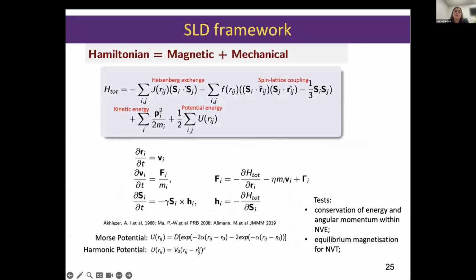The Hamiltonian has some modification, in contrast to a normal or vanilla atomistic spin dynamics simulation. We now include the energy coming from the lattice, so we have a kinetic and potential energy, and our magnetic interactions are now position dependent, as shown here by the exchange. We also introduce a spin lattice coupling term, as shown here, which allows for exchange of angular momentum between spin and lattice. We solve this coupled equation of motion as shown before.